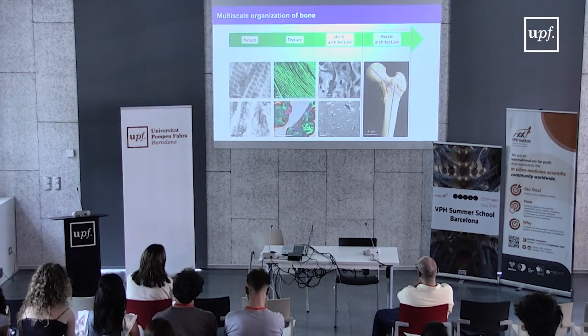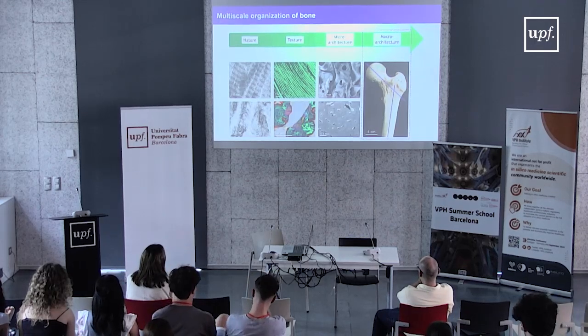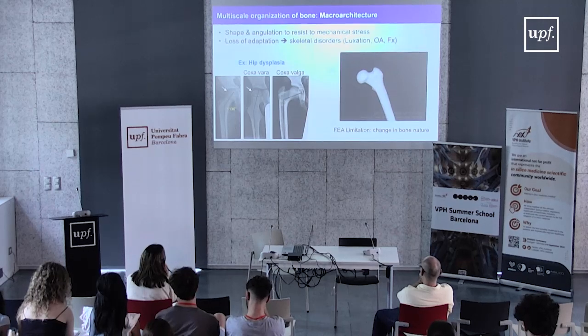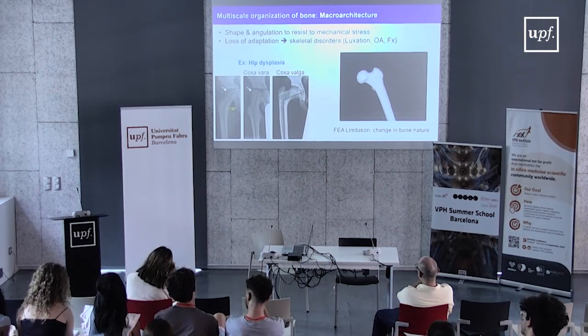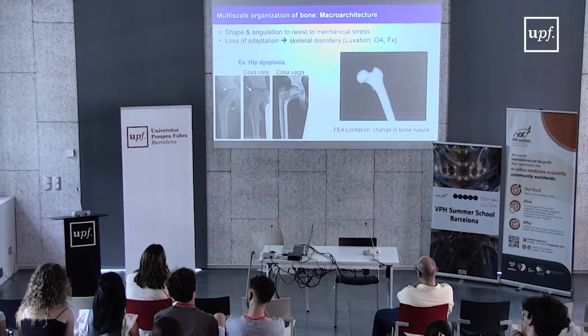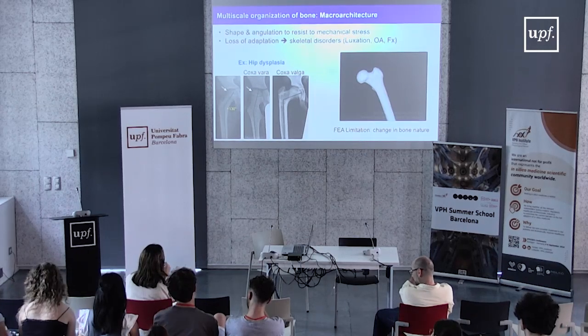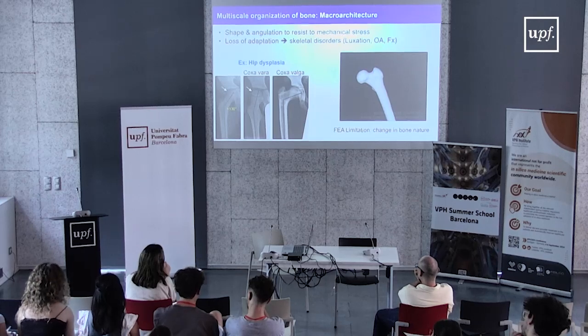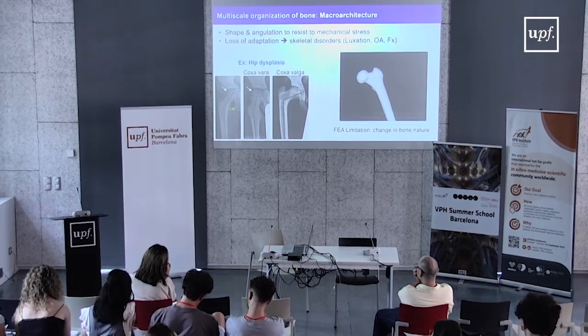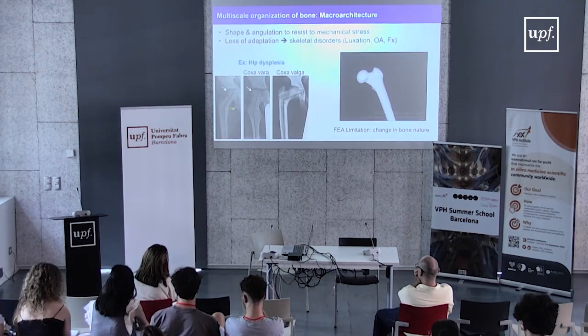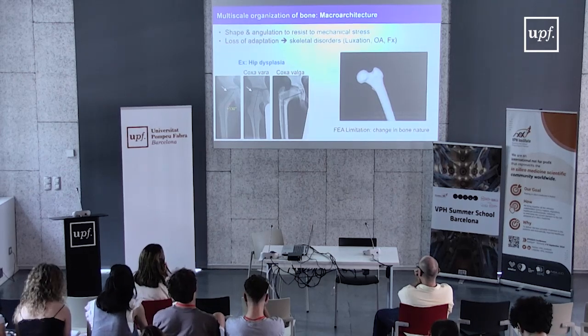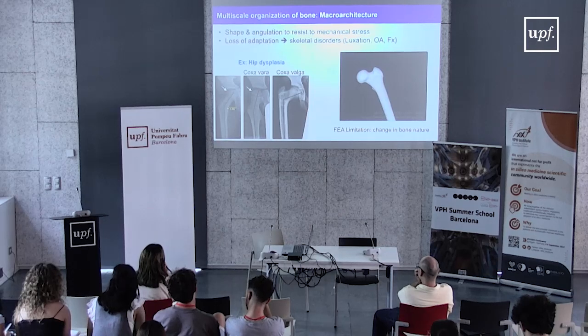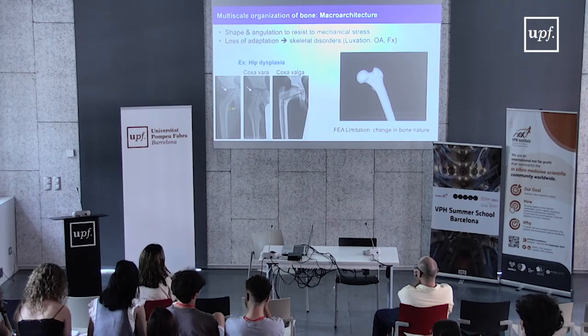Next, osteons and trabeculae will form the bone pieces and the macro architecture, and it's mainly a factor of shape and angulation to resist the mechanical stress. This needs to adapt through growth and life, especially in the elderly, who will start to have more bending than young individuals, so we will change, for example, the angulation of the femoral neck. It can be seen also in hip dysplasia, where it can lead to luxation, osteoarthritis, but also to fracture. An optimal angulation for the femoral neck is around 130 degrees, and you can have an extensive angulation, which is called the coxa valga, or a reduction in this angle, which is called the coxa vara.